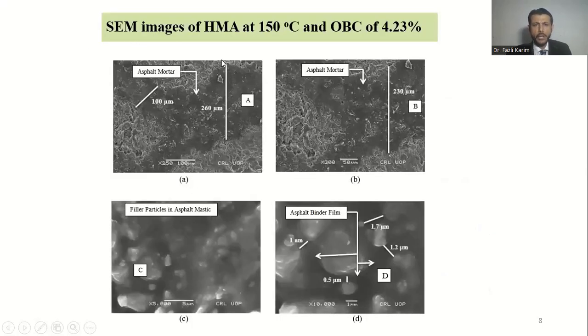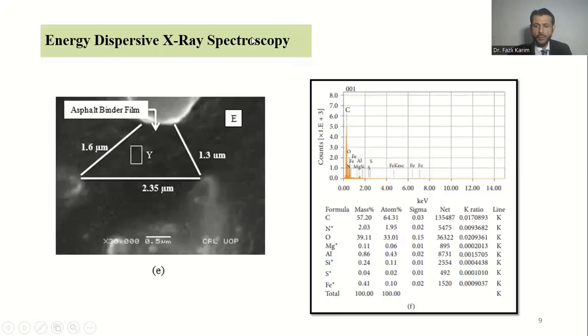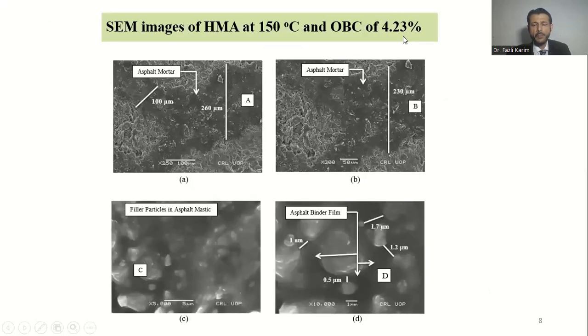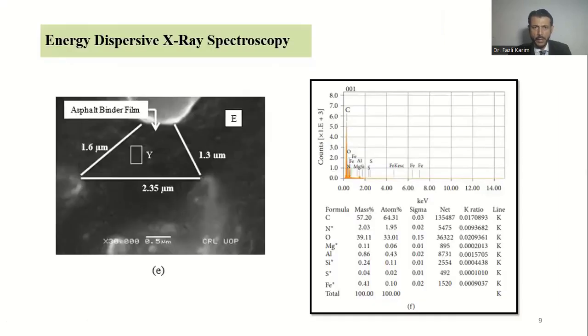Now again, the images of Marshall specimen when the mix design was carried out at 150 degrees centigrade, optimum binder content 4.23%. Again, asphalt mortar, and filler particles in asphalt mastic. And this is asphalt binder film ranging from 0.5 micrometer to 1.2 or 1.7 micrometer. Again, clearly visible asphalt binder film in the range of 1.3 to 2.35. Again, EDX was conducted to clearly indicate the existence of pure binder film.